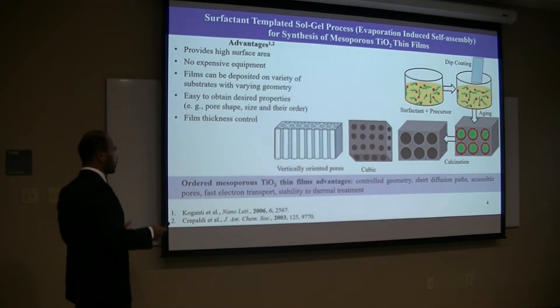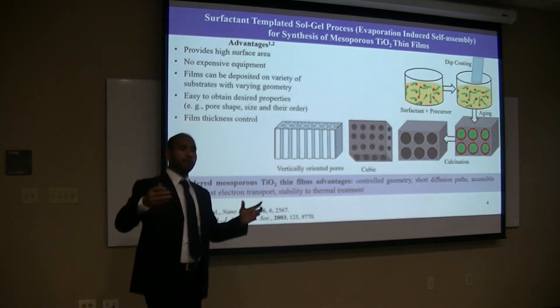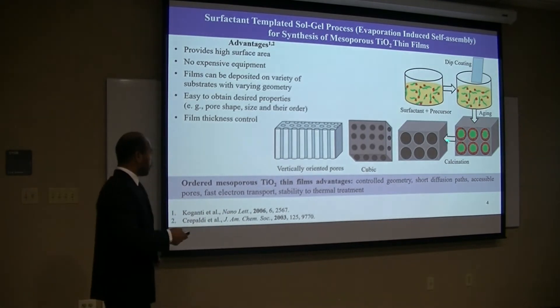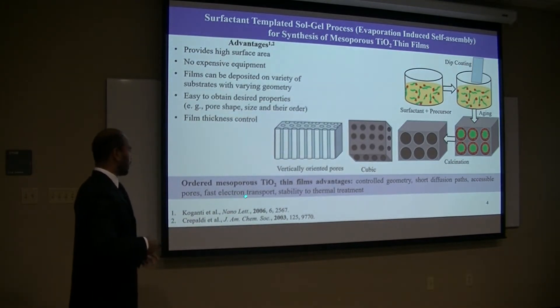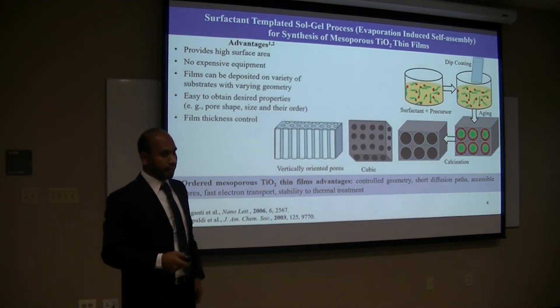The advantages of this mesoporous TiO2 include: we can control the geometry, it has very short diffusion paths which is helpful for the reactants to get into all the surfaces, the pores are accessible for fast electron transport, and by this orientation it can also help for better thermal stability.